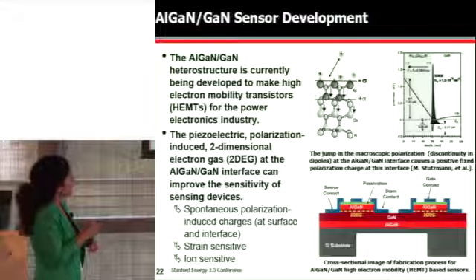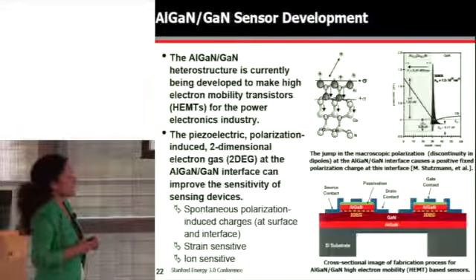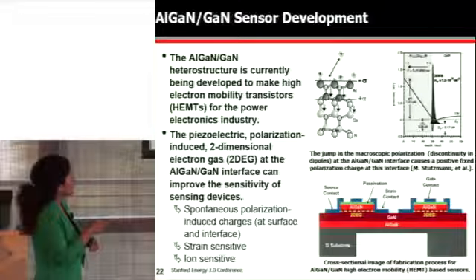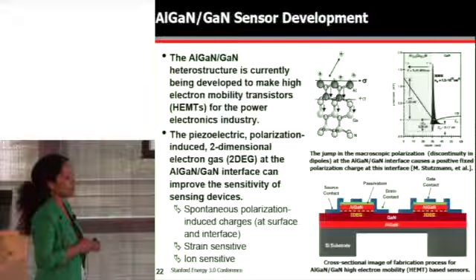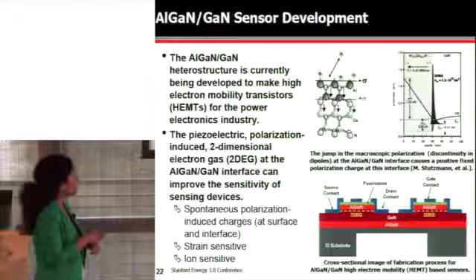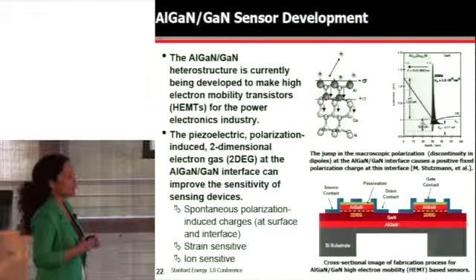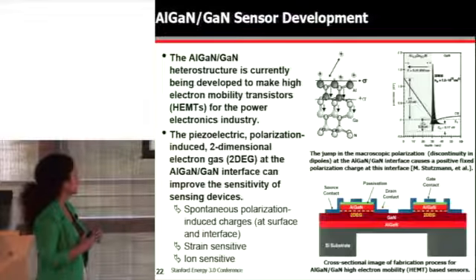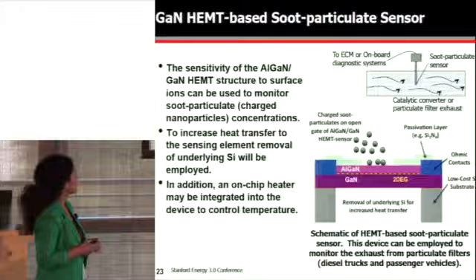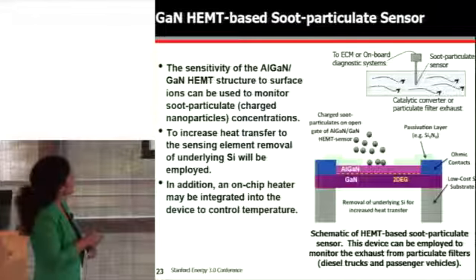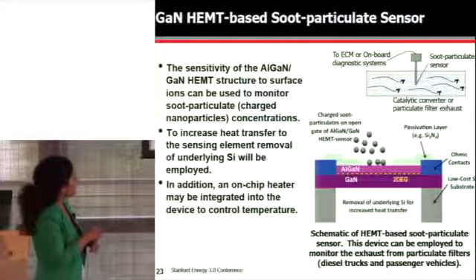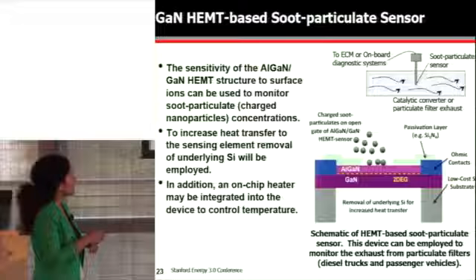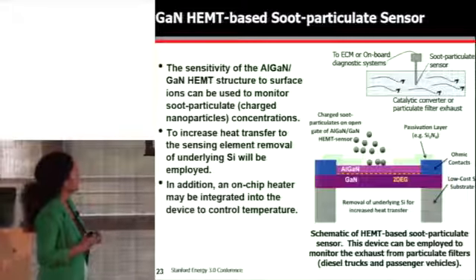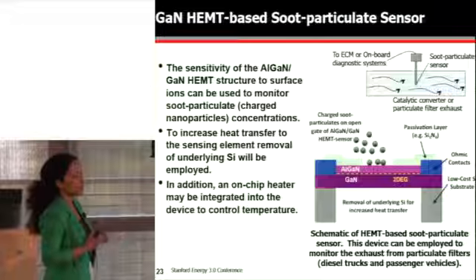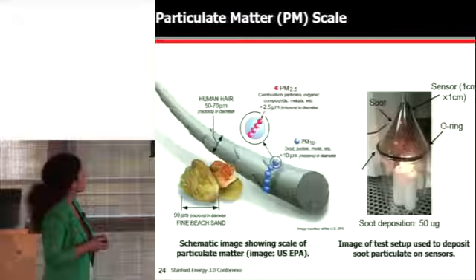What's interesting is that the surface of this structure is very sensitive to ions. So if I have charged species on the surface, that will actually impact the charge characteristics of the transistor. Likewise, if I apply strain to this transistor, I can also change the transfer characteristics. So now you can have a transistor that actually serves as a sensor. And so my group has recently started to explore that. This is a cross-sectional image of a soot particulate sensor. So again, imagine having these charged soot particulates deposited on the sensor. You might remove the underlying substrate for heat transfer, and this could be used in the actual exhaust of diesel vehicles or other passenger vehicles as well to monitor the soot.